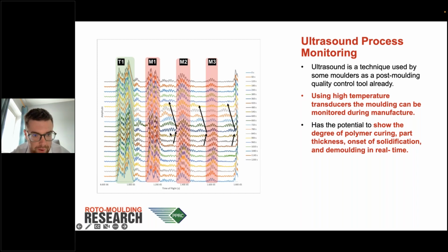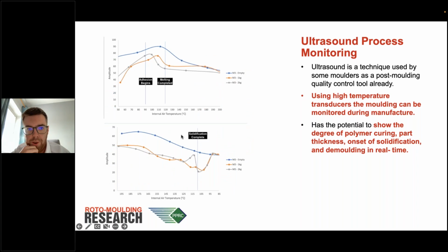But more interestingly than that, you can also monitor the amplitude of these signals, the strength of the signal that is returned back to the transducer. So if you imagine taking, for example, the peak of this signal right here and plotting how that changes between all of these curves, what you get is a graph that looks like this. So during the heating cycle, for an empty molding, you get this blue trace. And if you make a 1 kilo molding, you get the gray trace. And if you make a 2 kilo molding, you get the orange trace.